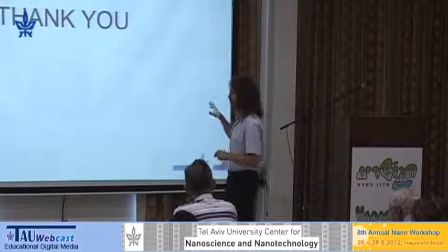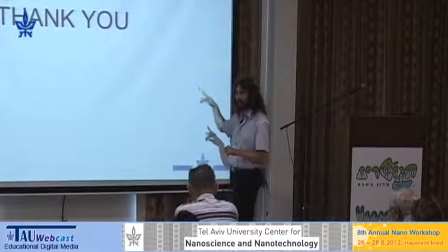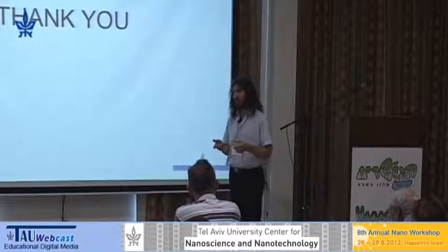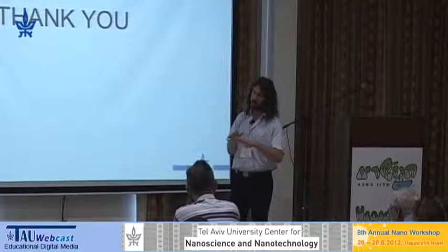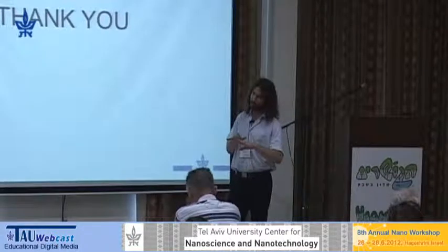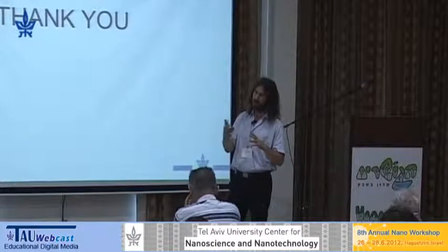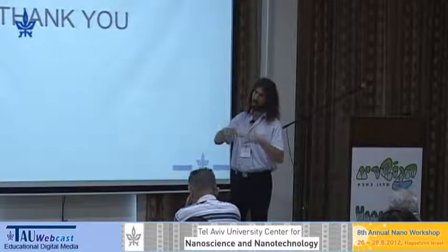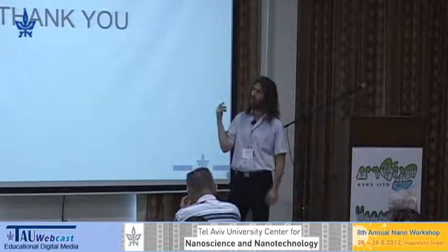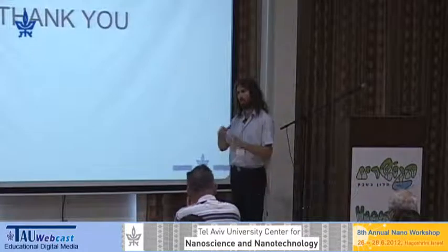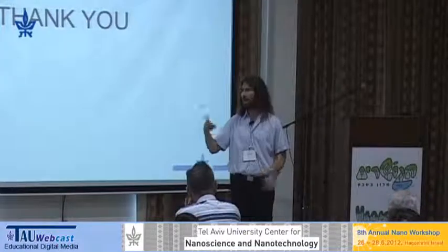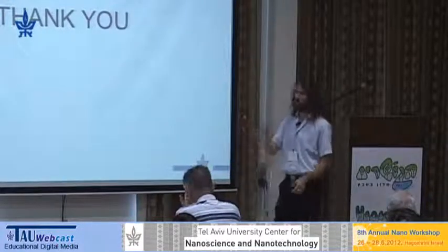I can tell you now, based on some experience with the other dendrimers that I haven't shown, that once you put all these dyes on, even with all the amines, they do self-assemble. But we were lucky enough to get a balance of hydrophobic and hydrophilic in the structure. So they self-assemble, but they're probably dynamic enough that some of the amines or some of the dyes are still exposed and accessible to the enzyme. Once you start chipping off these hydrophobic dyes, your dendrimer slowly becomes the exact opposite. It becomes more and more hydrophilic, and once it becomes more hydrophilic, it becomes more accessible.